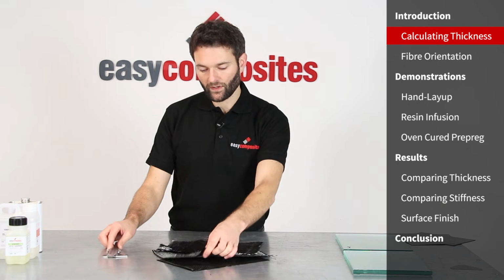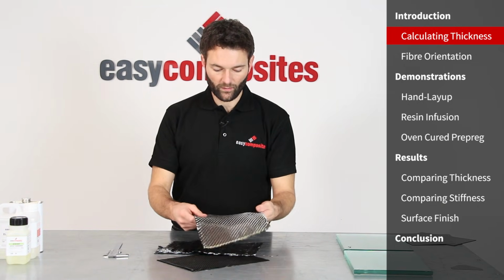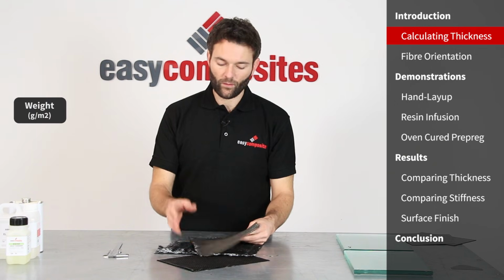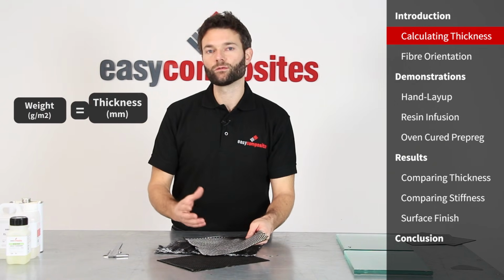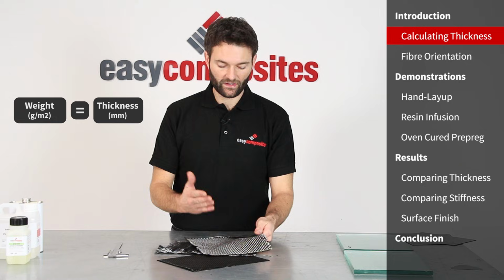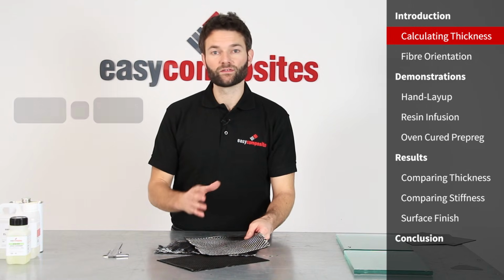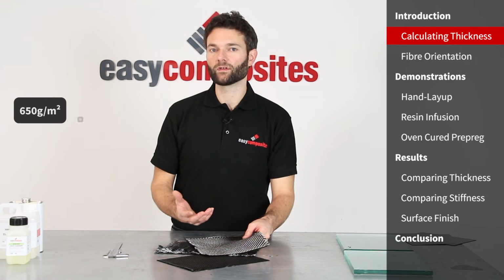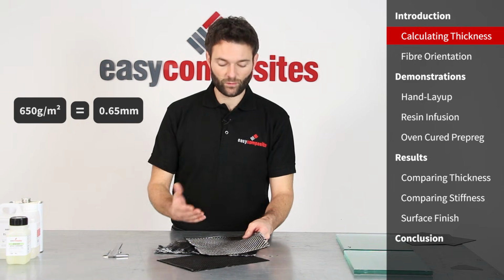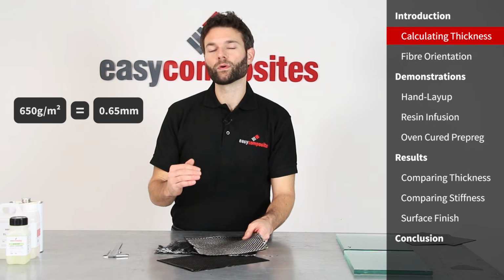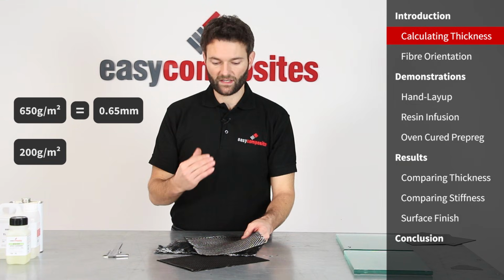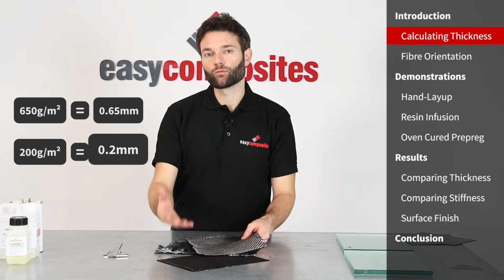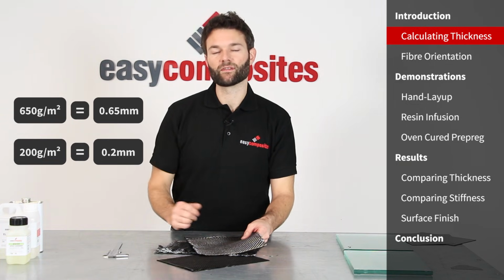And another quite interesting thing that you'll find with wovens particularly is that their weight in grams does tend to correspond pretty closely, certainly in a vacuum bagged laminate, to the thickness. So if you've got a 650 gram carbon, it will tend to result in a thickness of about 0.65 millimeters in the laminate. So 200 gram, around about 0.2 millimeters in the laminate.